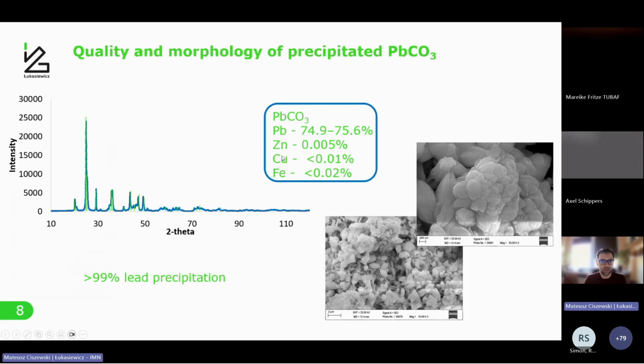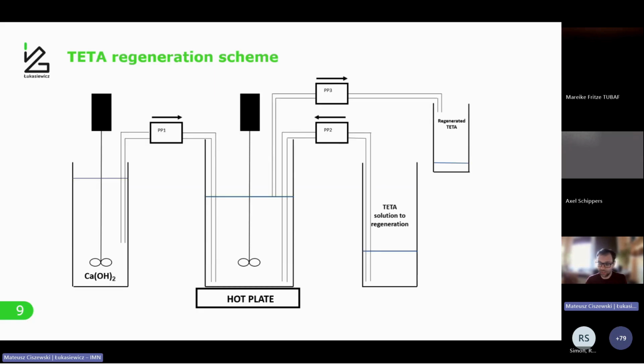Then the morphology and quality of this lead carbonate is quite important. As you can see, 75% of lead was present in this first lead concentrate. In fact, it was quite pure lead carbonate. And the regeneration scheme is based on a main reaction tank, which is supplied with the solution after carbonation and after precipitation of lead carbonate.